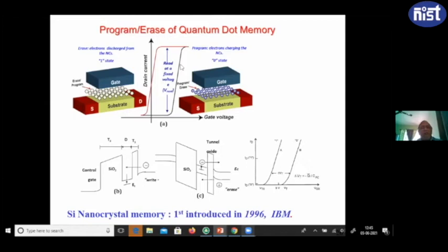There is a kind of hysteresis, and any kind of hysteresis shows up as a memory. So if you see here, when the device was in this state, this was the threshold voltage, and when the device is in this state, the threshold voltage increases by writing. Suppose this is 1 volt and this is 5 volt, and you use a voltage of 3 volt. If the device is in the off state, you see that at 3 volt there will be a lot of current. And if the device is programmed, there will be no current. So it will be able to read whether the memory is programmed or not. And that is this nanocrystal memory.